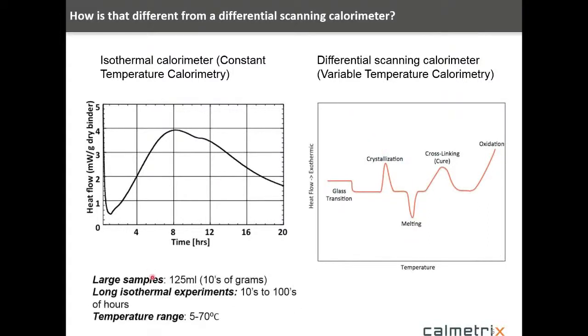In the case of an isothermal calorimeter, we're using very large sample sizes in the order of tens of grams, and we need large sample sizes because we're typically dealing with inhomogeneous materials, and secondly, the reactions that we're looking at are very low amounts of heat per gram. So by using very large sample sizes, we can get a high absolute signal that then the instrument can pick up.